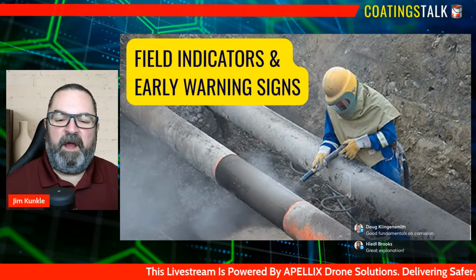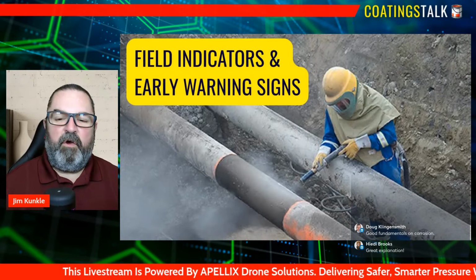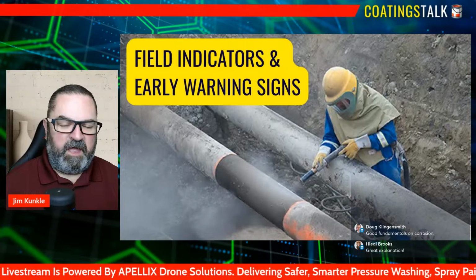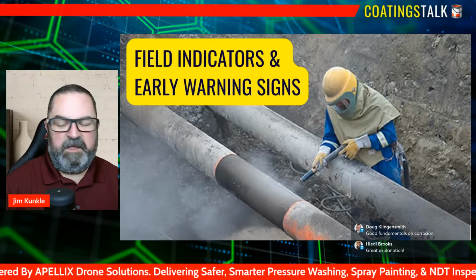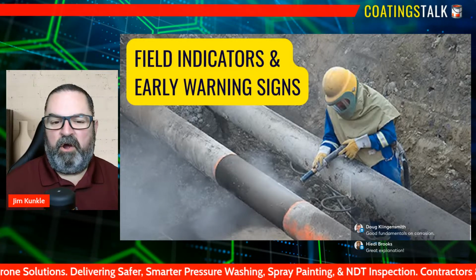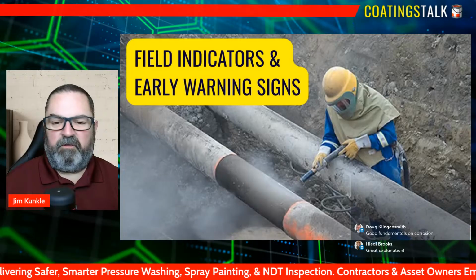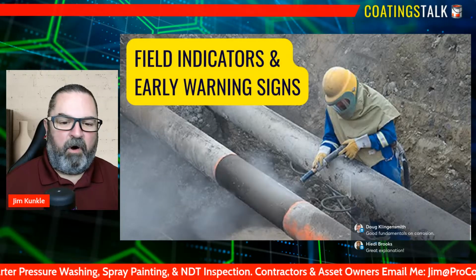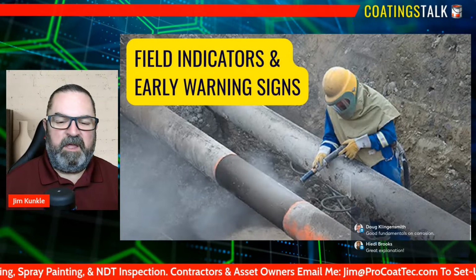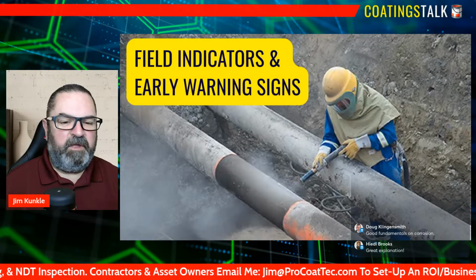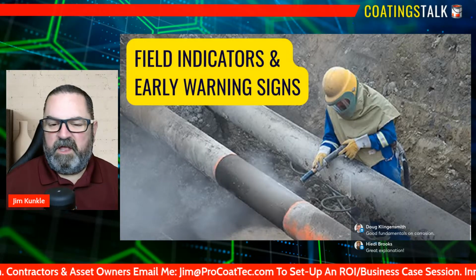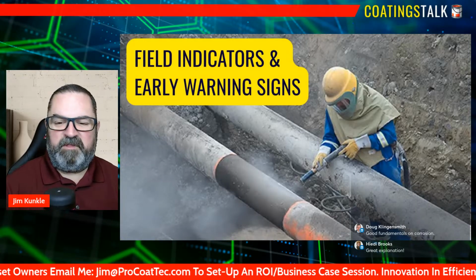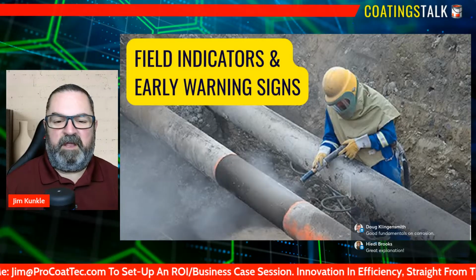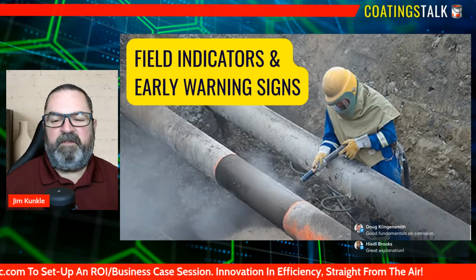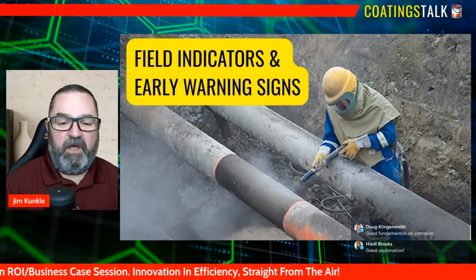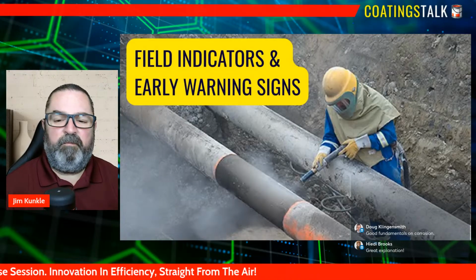Another critical area of focus is the presence of moisture, water traps, and environmental stressors. Inspectors should look for standing water, condensation, salt deposits, or debris buildup, all of which can create microenvironments that accelerate corrosion. Pay special attention to welds, edges, bolts, clamps, and areas where two surfaces meet, because these locations often experience higher stress and are more prone to coating breakdown.